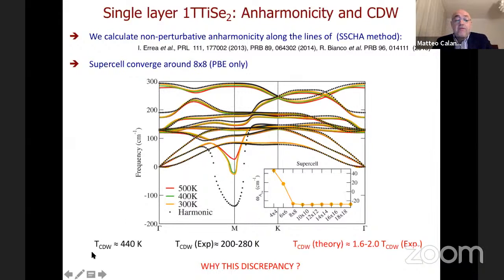However, the instability is removed around 440 Kelvin, and this is a calculation for a single layer that is suspended, so freestanding with no substrate. And the experimental one is around 200 to 280. You would think that this is a very bad agreement, but it's very difficult to achieve accuracy of the order of 200 Kelvin, because you can try to figure out how much is 200 Kelvin in eV. So 300 Kelvin is 25 millivolts. It means that your free energy must be more accurate than 25 millivolts.